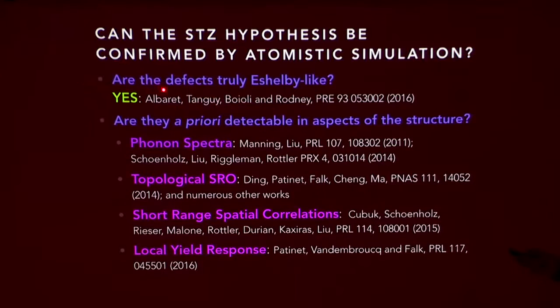And so one question you could ask is, are they Eshelby-like? One thing that's been noted about them is the expectation that they behave as if you've put an inclusion into an elastic medium. That if you have deformation locally in some small region of the material, this should be equivalent, according to Eshelby, to taking out a region of the material, taking it through a deformation, stuffing it back in the hole, and then letting it go, because it's constrained by the surrounding material, and that should have a particular elastic signature.